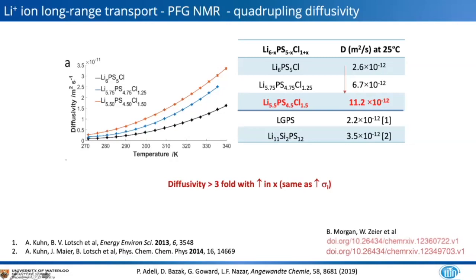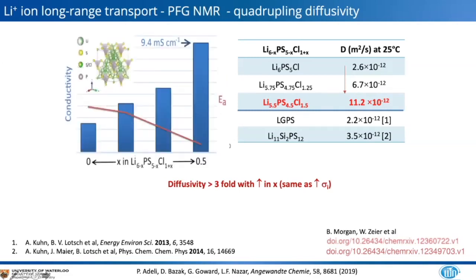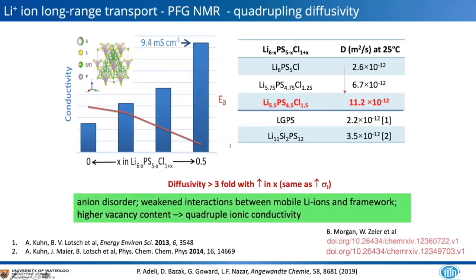And so this is just a plot of the diffusivity obtained from these PFG measurements, and you can see that it's definitely the highest for the chlorine-rich phase. And the value of diffusivity of 11 times 10 to the minus 12 is actually higher than that in LGPS or in this lithium silicon LGPS type, or this other type of structure. So the diffusivity is about more than threefold, and that basically correlates exactly with the increase in the conductivity that you see plotted here in this bar graph. So the take-home message is that the anion disorder and weakened interactions between the mobile ions and the framework lead to a quadrupling in the ionic conductivity.